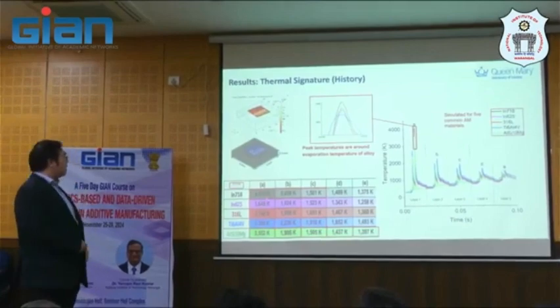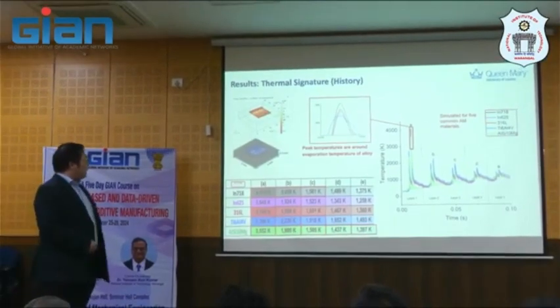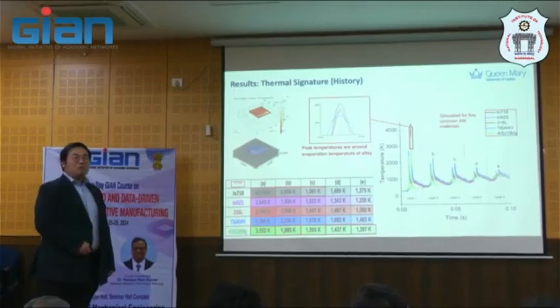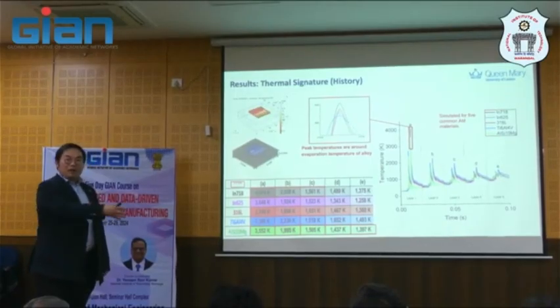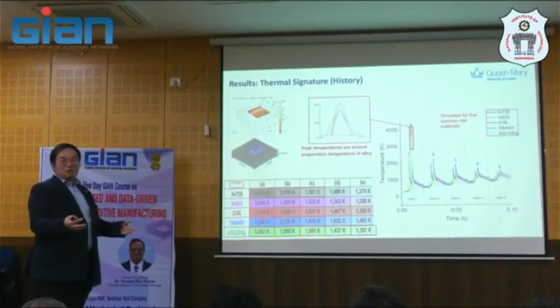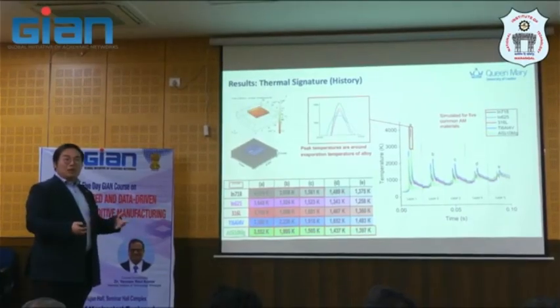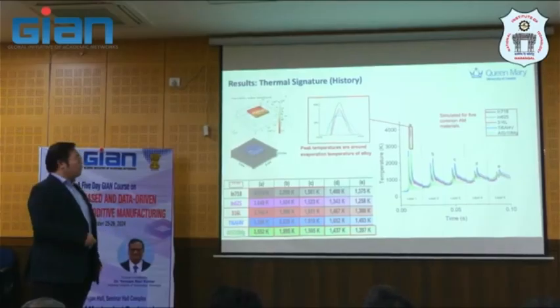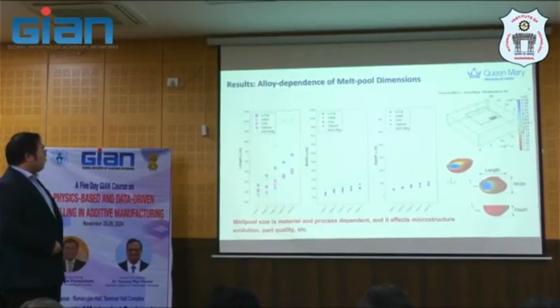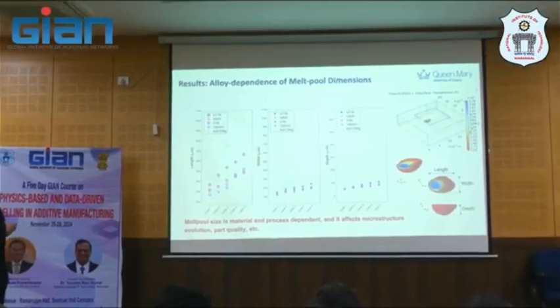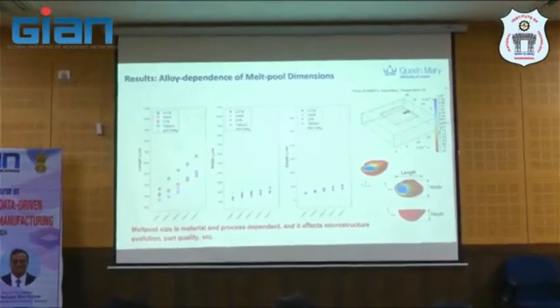For example, there's some characteristic that nickel probably needs 3 layers, titanium probably 3 or 4, but aluminum probably 15 layers of remelting every time at the optimum condition. So this information is also important for developing a further model as well. So we quantify this alloy dependency of the melt pool dimension as well.